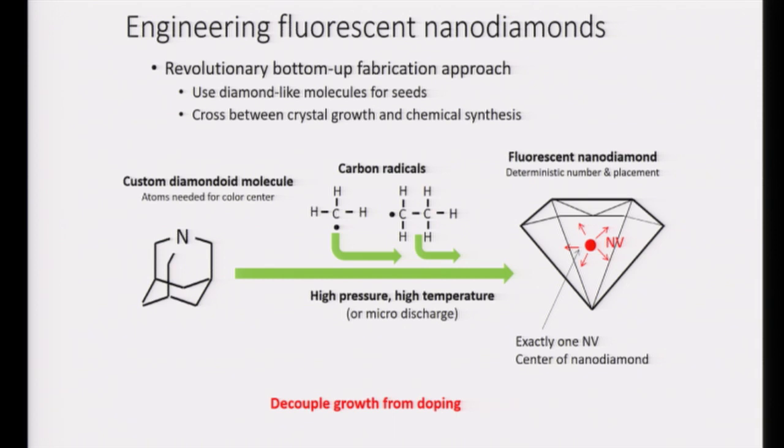It turns out that CVD involves a plasma, okay? And even when you've optimized the plasma conditions, you're doing a growth and etching in parallel, okay? And what's happening is that etching destroys the seed molecule. And so there's really no way this can work. I mean, I tried everything. I even tried flowing vapor plasmas. I tried downstream injection. I tried all kinds of things. And after about 10 years, I finally gave up. It couldn't be done. So what do you do?